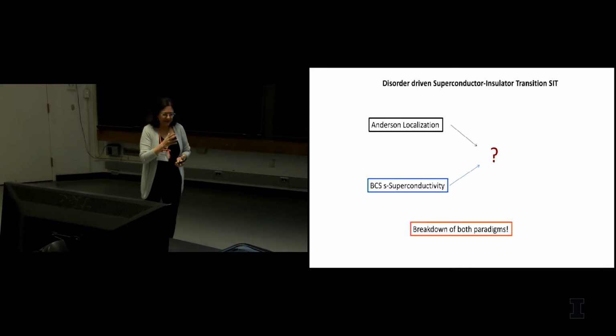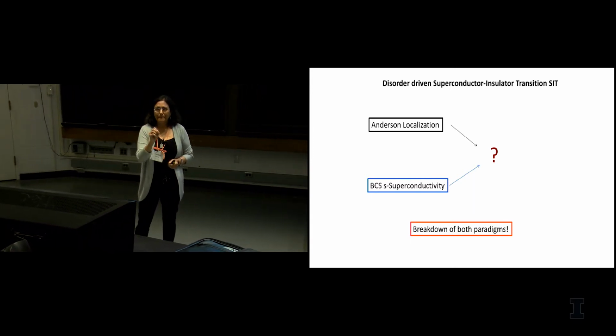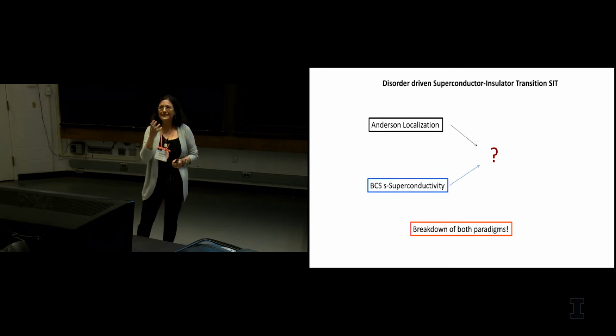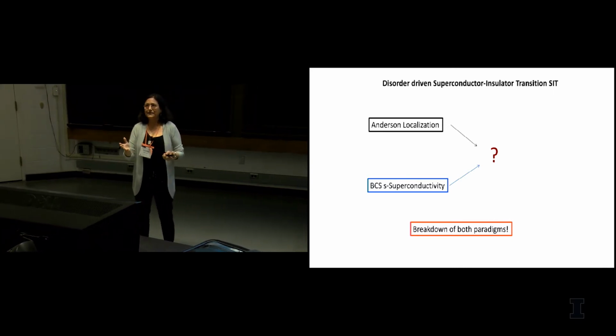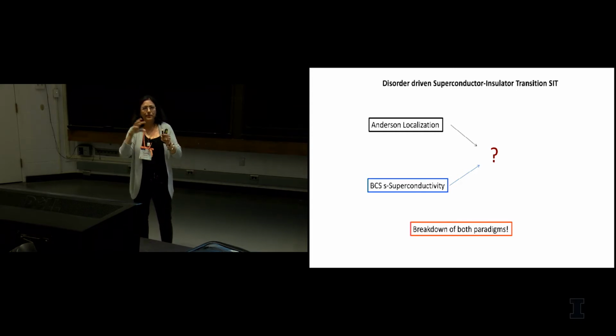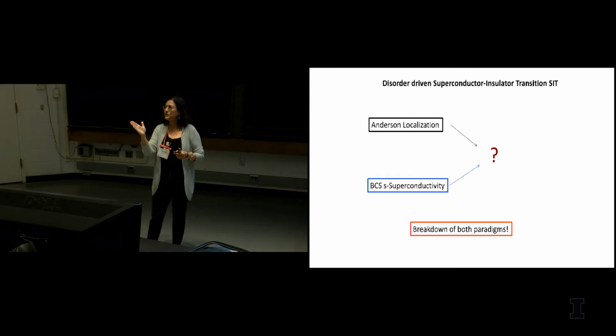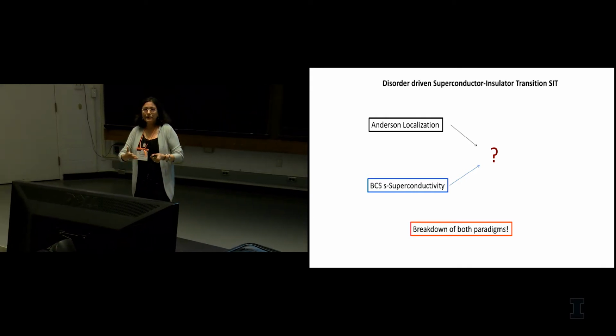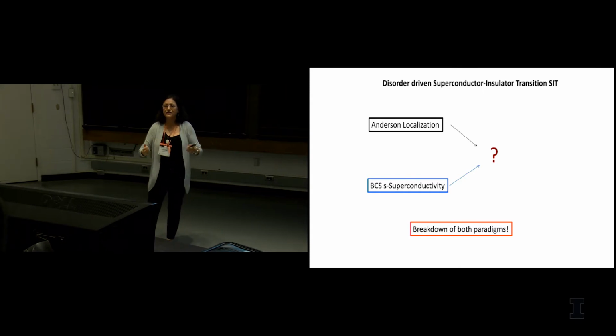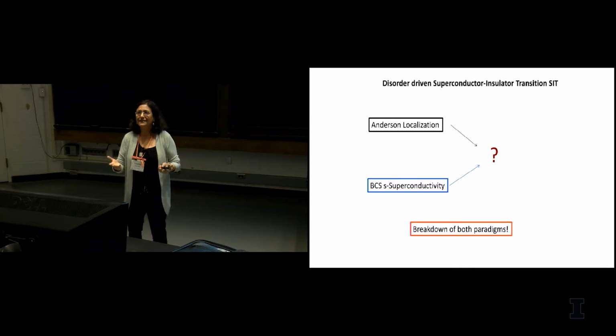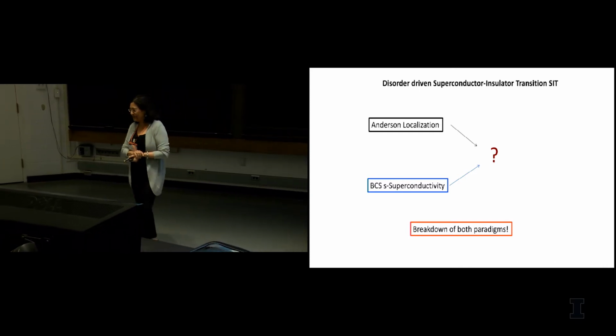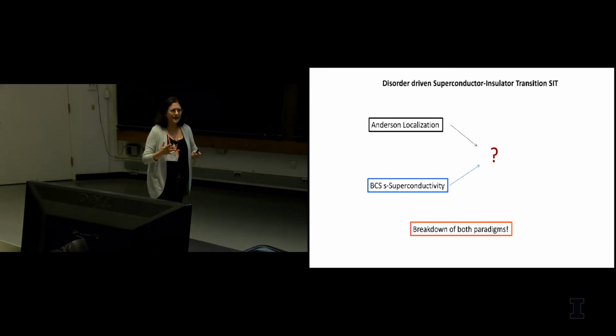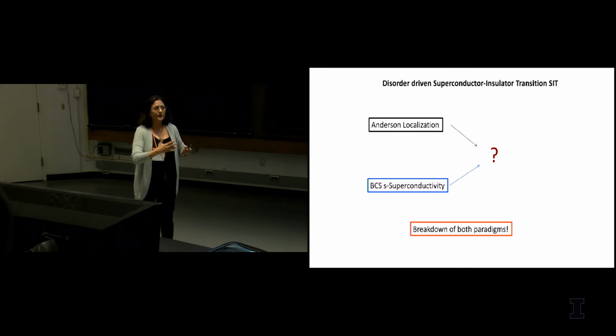And one of the things that struck me at that point was the effect of disorder. So if you have a D-wave superconductor, they were supposed to be extremely sensitive to disorder based on Abrikosov-Gorkov and their calculations. And it's clear why that is the case, because you have these lobes with different phases, positive and negative phases in the D-wave superconductor, and disorder would typically scatter you from the positive lobe to the negative lobe, washing out superconductivity. And yet, undergraduates were working in labs, mixing and baking and shaking and making these cuprate superconductors. So clearly, they were not sensitive to that disorder. So the question was why? And I was kind of coming out at that point more toward the S-wave direction, just because of their ability to sustain so much disorder.